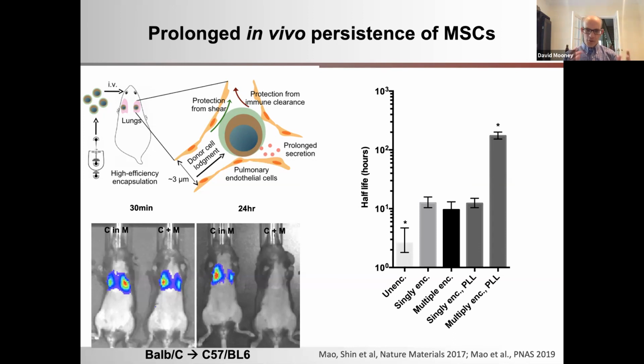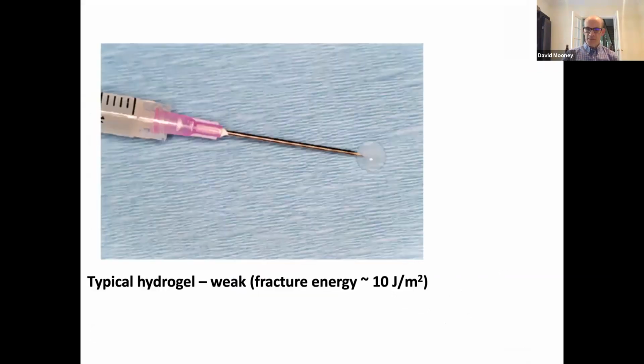So hopefully this gives you a little flavor of how we're using mechanics of soft materials to control biology in a couple of settings. However, as we were going down this path, one of the things that became clear to us is that these hydrogels we've been using, and this is probably not a surprise to anyone in this audience, are actually quite weak materials, with a fracture energy of about 10 joules per meter squared. And this really limits their applications in many settings.